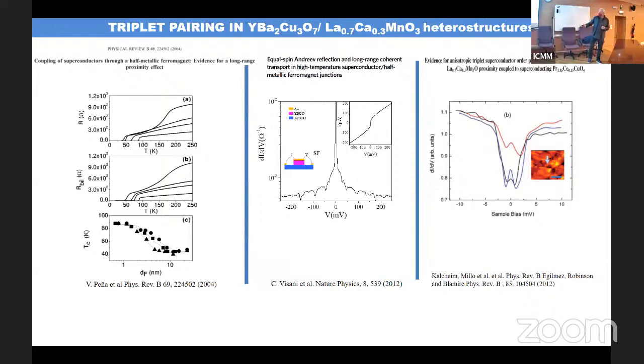A bit later, Cristina Visani, another of our students, was doing a postdoc with Javier Villegas in Paris. We measured tunneling transport in bilayers, right? And we found this oscillatory behavior at energies above the gap of the superconductor, which scaled with the thickness of the ferromagnet. These are McMillan-Rowell oscillations and demonstrate coherent transport in the ferromagnet. So this was taken as strong evidence for the existence of the triplets.